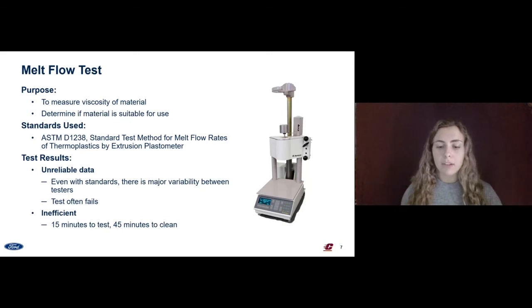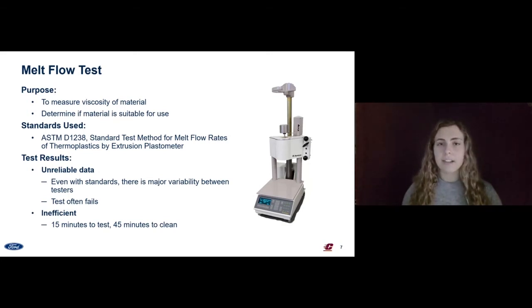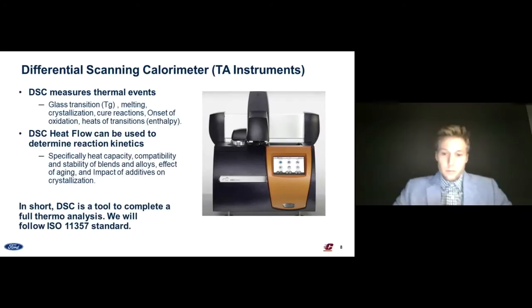Not only does the melt flow test create inaccurate data, but it is also very inefficient. Our Ford contact said it takes 3 times longer to clean the machine than to simply conduct the test itself. Ford wants efficient and reliable data, and the current process for melt flow testing cannot do either. Therefore, our group has set out to find a solution to this problem.